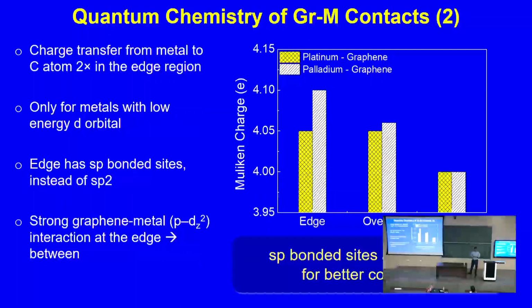Now we tested whether it works for all metals or only for select metals. For that, you do a Mulliken charge calculation, which tells you how much charge sharing there is in that bonding process, and also whether there is bonding or not. When we tried palladium and platinum, palladium has a 4d orbital, platinum has a 5d orbital, and the energy of the 4d orbital in palladium is very close to the 2p orbital of carbon. So we found that in the case of palladium, there is a higher amount of charge sharing in the edge area versus the overlap area, which means a better bond is formed in the edge area.